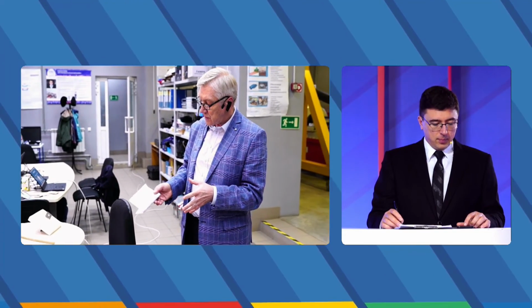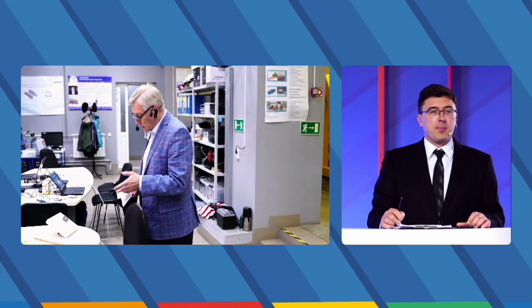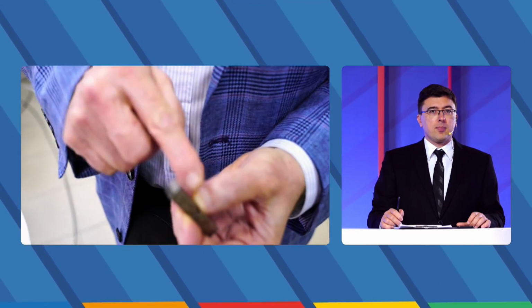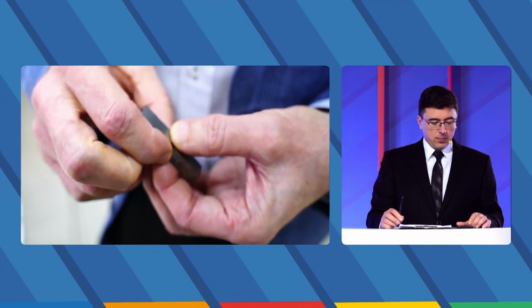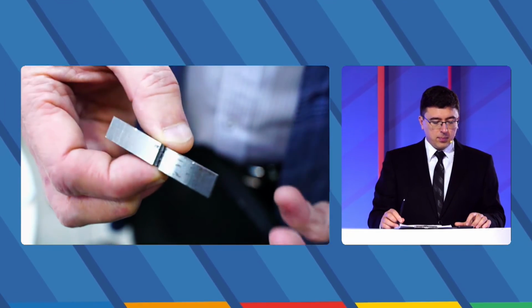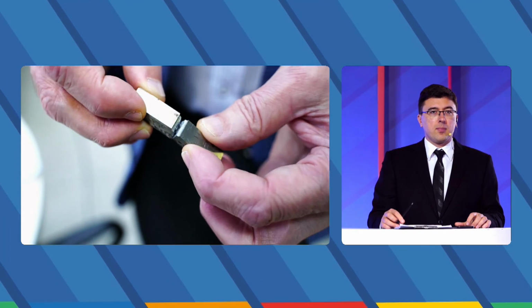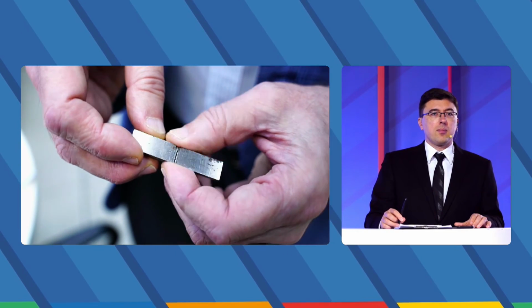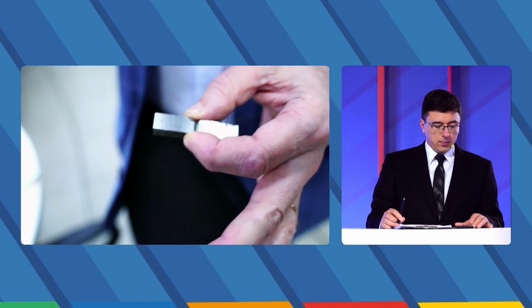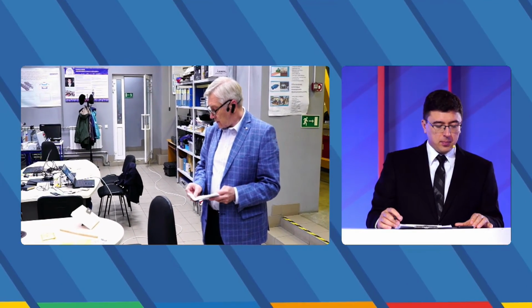All tests are provided with standards, and the dimensions are according to standards, especially for toughness. We have this sample with size 10 millimeters by 10 millimeters and 60 millimeters long. The groove is special, in the center, to locate the crack in the needed place, and all the dimensions are according to standard. I don't remember the real number of this standard, but it's very well known in scientific literature. There are a few more questions. What was the yield strength of the sample, if you remember? This is low carbon steel with yield strength about 300 megapascal.